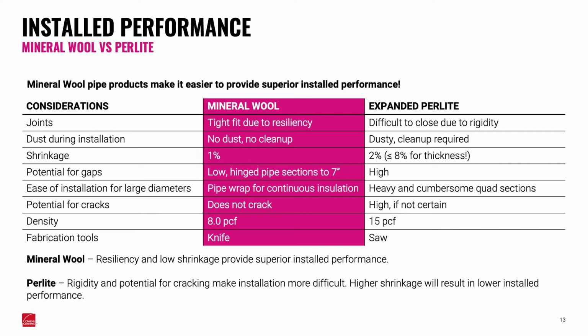As far as the potential for cracks, mineral wool doesn't crack because it's a fibrous product, but something like expanded perlite, because of its fragile nature, higher likelihood that you're going to have some breakage or at a minimum cracks, which create all kinds of things. So maybe as the product shrinks, that makes that gap larger, or cracks are going to form as the product on one side is hotter than the other side, and you get cracks there. So that's part of the reason that mineral wool performs so well thermally. And again, we talked about the density being lower, so it's much easier to handle and install.